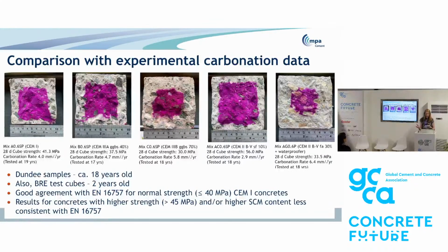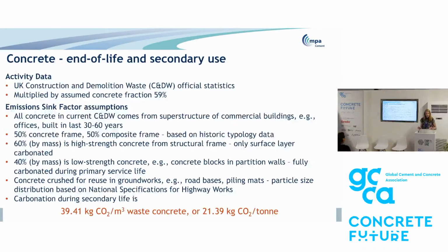However, for higher strength concrete, so strengths greater than 45 megapascals, we actually found the results were slightly less consistent, and that was one of the recommendations we then had later on, was to do a bit more work around those higher strength concretes. So very quickly, the end of life and secondary use.